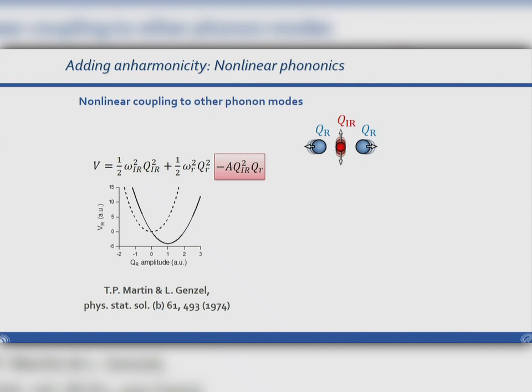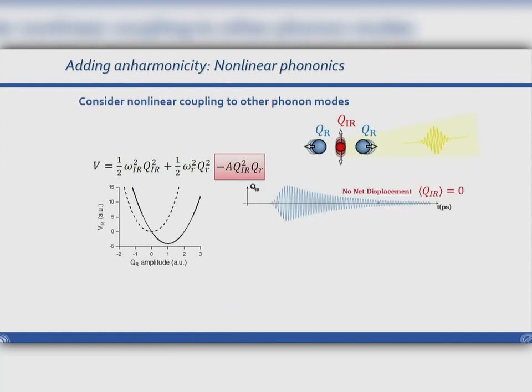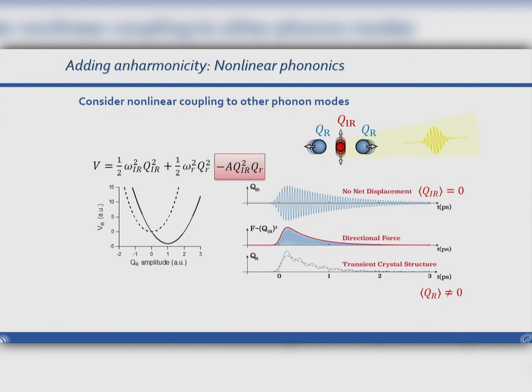And what this does, shown here in a frozen phonon example, is that if Q_IR is fixed but finite, you will shift the potential of this Raman mode from its equilibrium position to a new position. So this allows you to change the crystal structure along the coordinate of the coupled mode. And if you now consider this in the time domain, where we can drive this mode with an intense light field, so you see here the oscillations that I showed you before, this puts a directional force onto the Raman mode, and thereby it can induce a transient crystal structure for a short lifetime. Definitely this is no longer oscillating around zero, and therefore it allows you to dynamically drive a distortion in the lattice where you can have different magnetic or electronic properties.